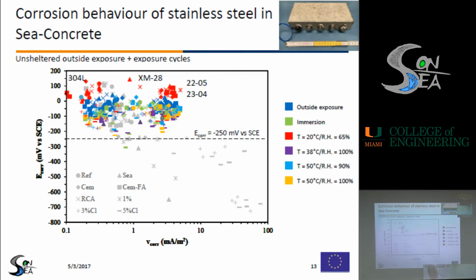This figure summarizes the results obtained on the different types of stainless steel and shows the relationship between the corrosion rate and the corrosion potential. The gray symbols represent the results obtained on the carbon steel. These are the results obtained on the stainless steel 304, and we can observe that for the different types of concrete represented by the different symbols in the different exposure conditions, high corrosion potential and low corrosion rate were always measured, indicating that corrosion did not occur even when the bar were embedded in the concrete with the highest chloride content, so 5% of chloride, and when exposed to the harshest environment, so the highest temperature and the highest relative